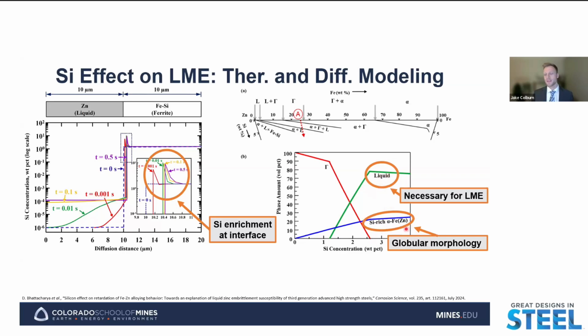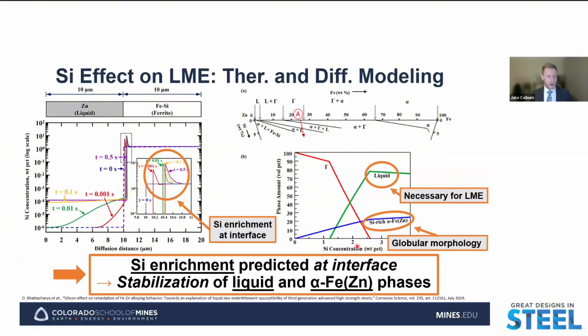But if we're also stabilizing the alpha iron zinc phase instead of the gamma phase, we're stabilizing a phase that, especially in these lower volume fractions, is likely to form in a globular morphology. So as those small islands that we saw in the STEM image, this is what we see here generally with the alpha iron zinc phase. And so we could say that as we're increasing the silicon concentration in the substrate and then getting enrichment at the interface, we are going to have a detrimental situation for LME susceptibility by inhibiting the reaction of forming the gamma phase, but then also stabilizing these two potentially detrimental phases for LME susceptibility.